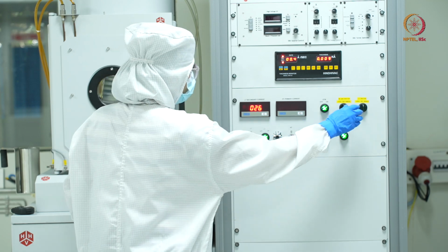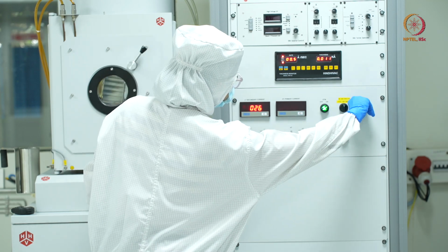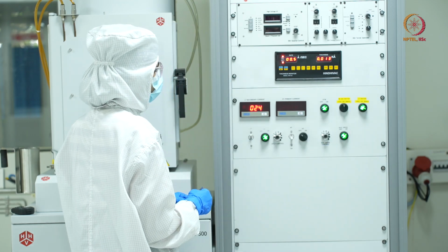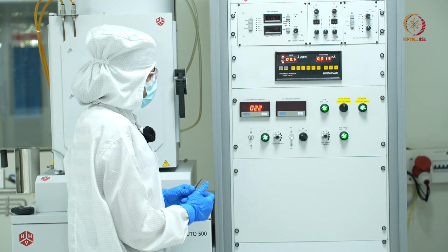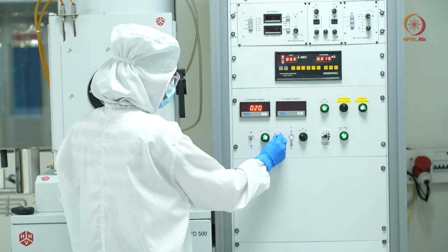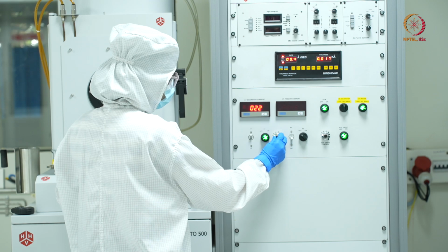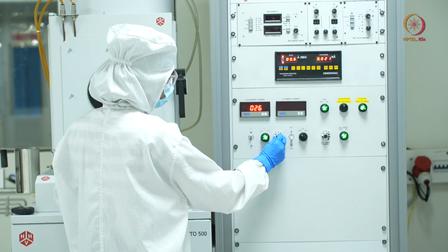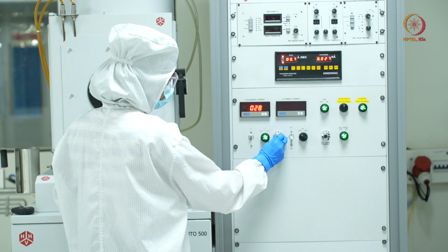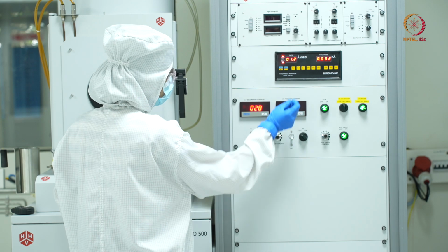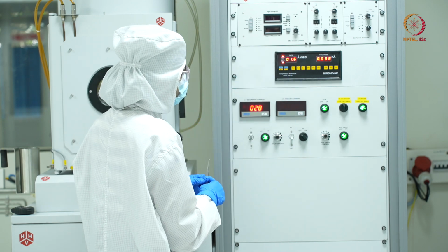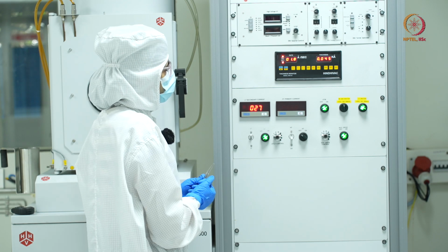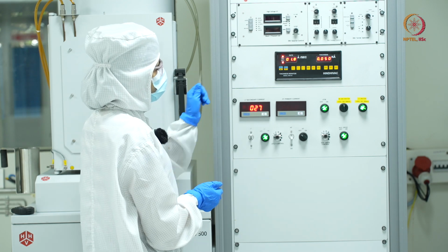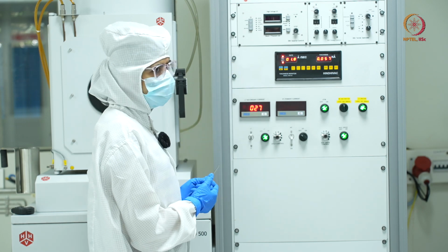And I'll open the shutter. To increase the deposition rate, I can increase my current furthermore to 25, which was already there. I can go to 27, 28. As you can see, the deposition rate has increased, and I'll just wait for 1 minute or so to get a good quality, good film thickness.